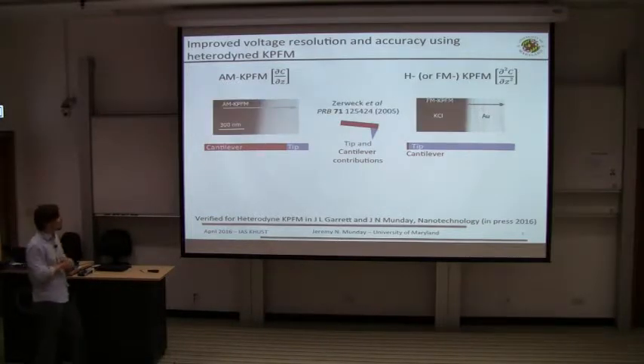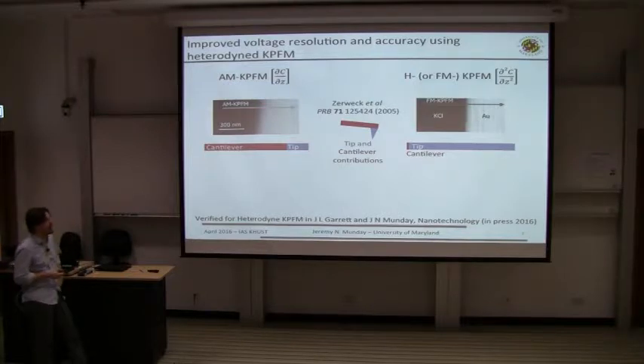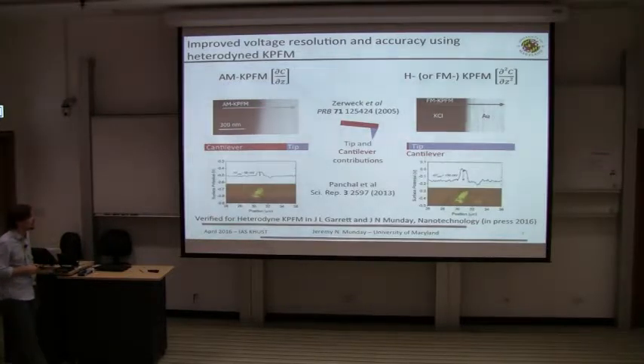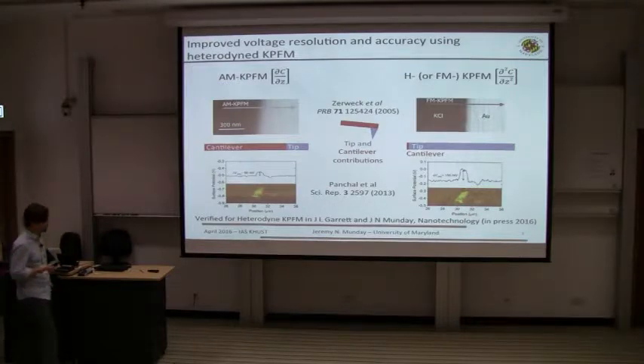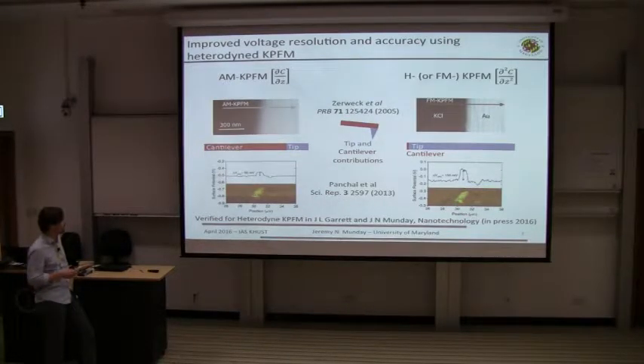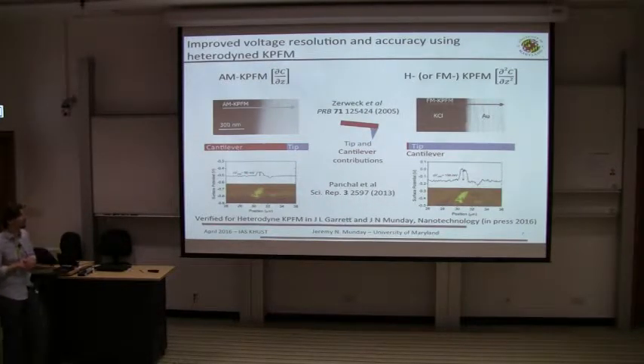There's some nice work back in 2005, comparing these quantitatively, these different methods, where you can see that you get improved spatial resolution here. You can more clearly see the transition here from one material to the other using this frequency modulated method. And there's also been some more recent work, I guess a lot of different works, but here's another example, looking at some graphene layers and how the potential varies as you go across. And so you also see that in addition to the spatial resolution that you see improved here, there's also improved contrast that you're getting when you start using these frequency modulated heterodyne techniques.